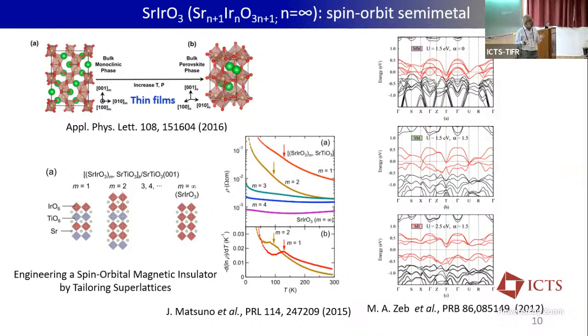So as I mentioned, one should expect from the previous slide, depending upon the dimensionality, it should be metallic. But look at the data here. It has been found that SrIrO3 is not metallic, rather it is semi-metallic in nature. And there have been calculations which tell that it's not only semi-metallic, but it is a Dirac semi-metal.